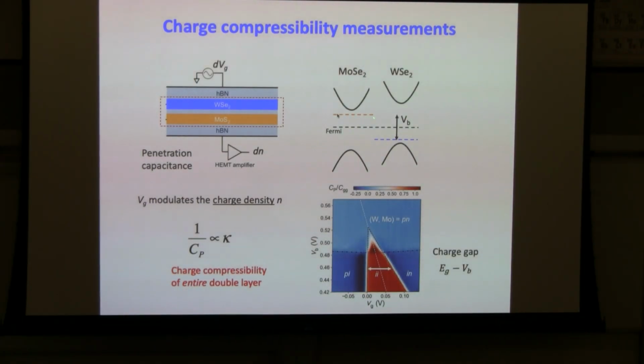You can apply a bias that separates the electron and the hole chemical potential, and that will reduce the effective charge gap. This is the map of the penetration capacitance, or if you like, the compressibility of the system, or the incompressibility of the system, as a function of VB and VG. Red means incompressible, and you can directly read out the charge gap by the VG difference, by this arrow here. So with increasing VB, you are decreasing the charge gap, and finally the charge gap closes at this point, and there's no more charge gap in the system. And finally, the system becomes compressible in the blue region. Okay, so I hope it is clear.